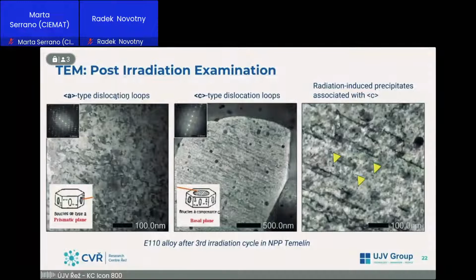So here are some examples of A dislocation loops in microstructures which are formed at low fluences. This is the first image. The second image, there we can observe the C dislocation type loops which are formed as fluence raises. And then we can observe at the high magnifications the irradiation-induced precipitates associated with these loops. And as I told about the radiation growth of the fuel rods, this C type of loops are responsible for radiation growth. So that's the way we evaluate after different neutron fluences compared to the mechanical properties and the radiation growth evaluation.